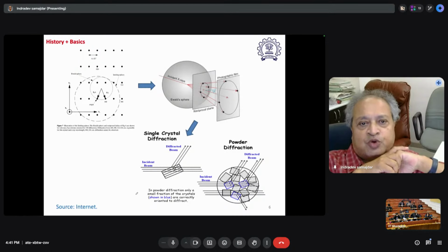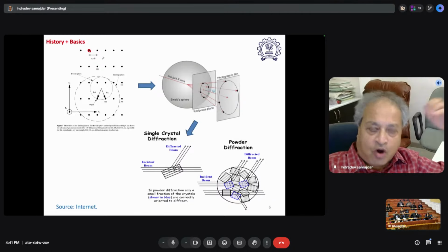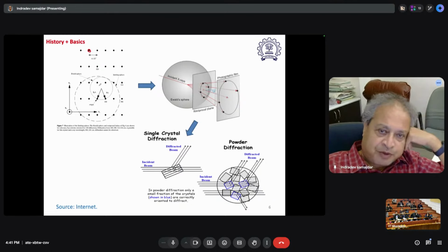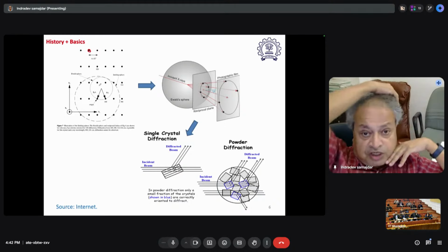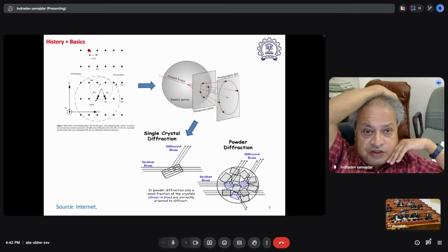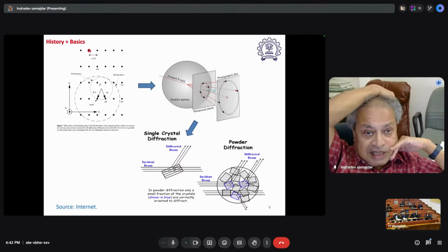It's in reciprocal lattice space, where the distance between these diffraction spots relates to atomic planes. The distance between the atomic planes gives you the d spacing. The Ewald sphere construction, which is 1/λ, intercepts some of these reciprocal lattice points and they meet the Bragg condition and diffract.